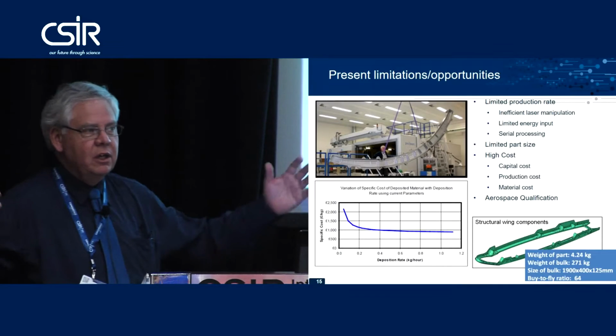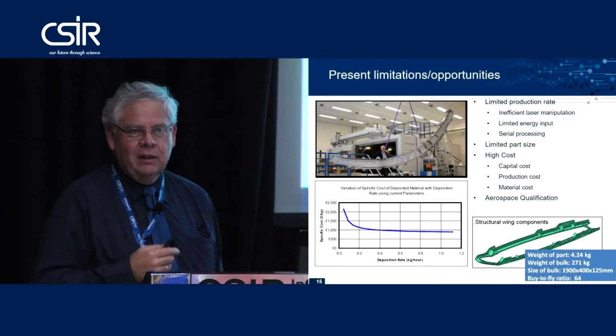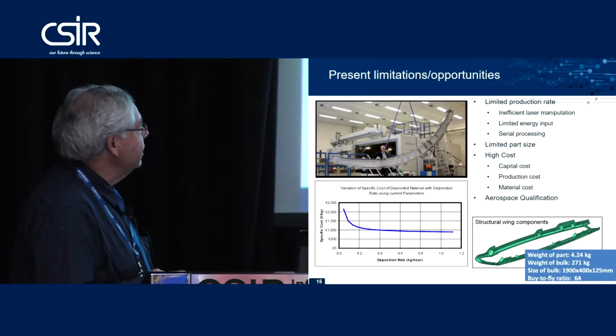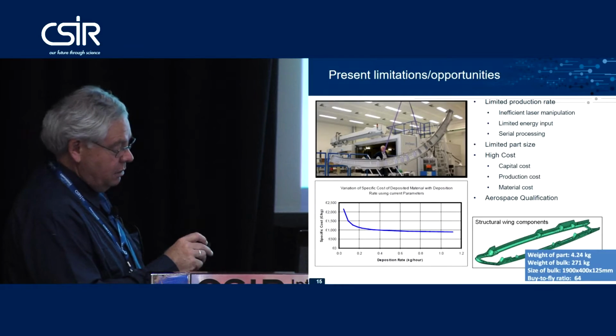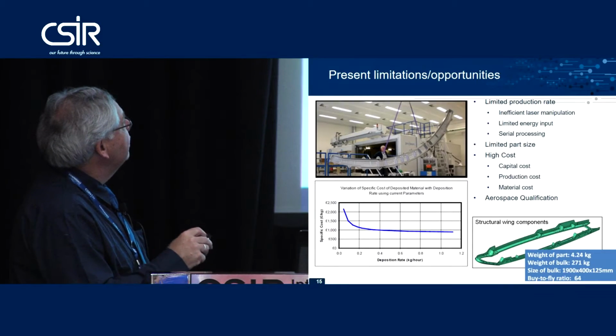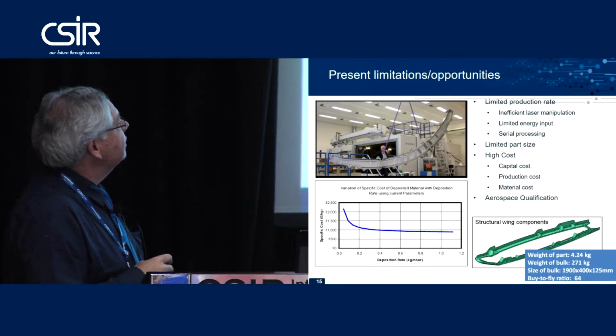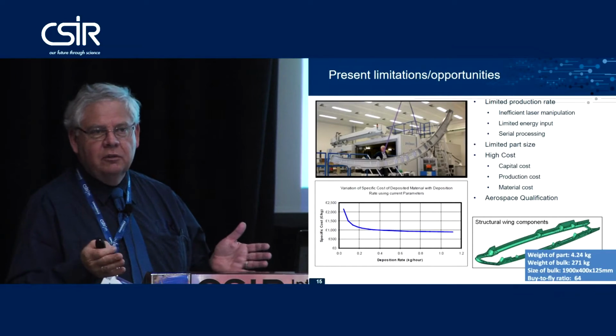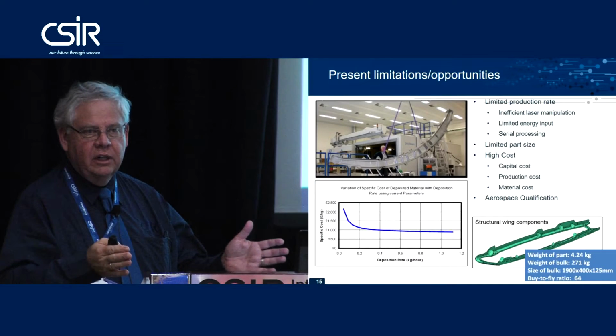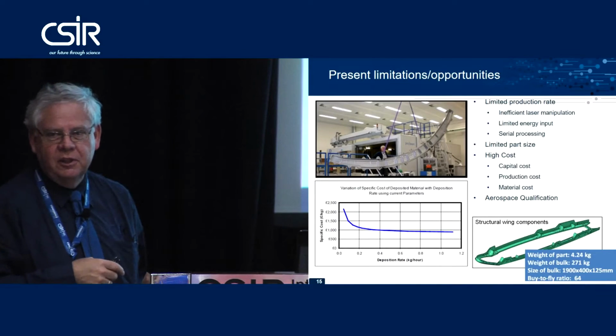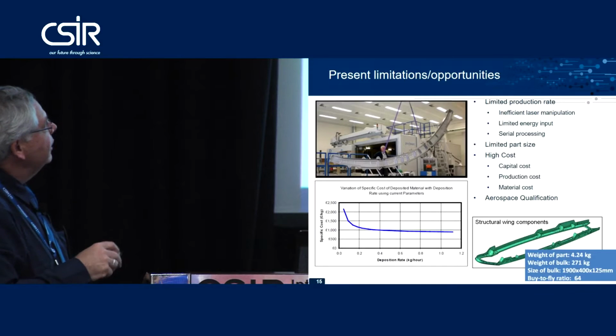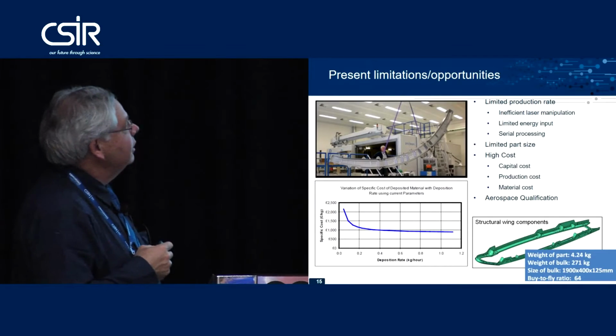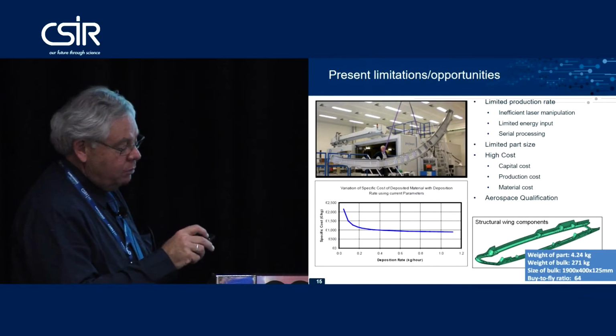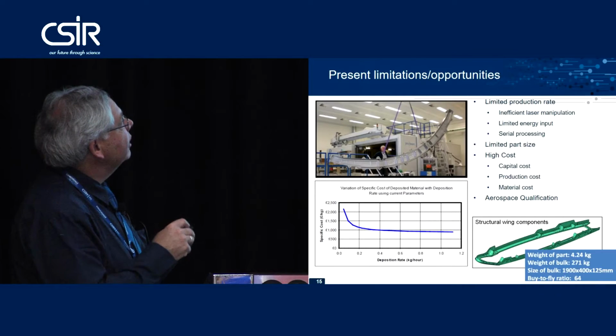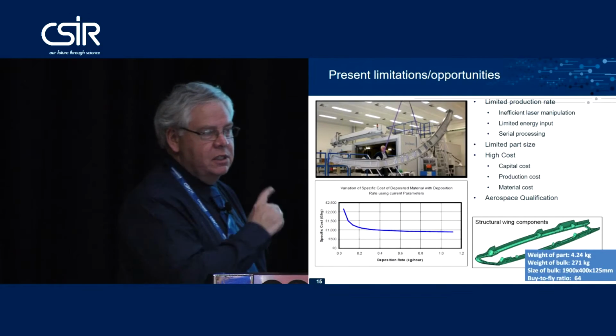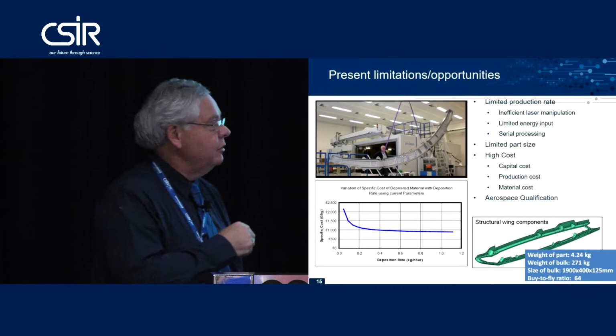So if you start thinking about very large aerospace components, you cannot really do this with additive manufacturing as yet. Just to give you an example, this is a part which I think is from Boeing in titanium, which is machined from billet. Currently, commercial systems in additive manufacturing do 300 or 350 by 350 by 350 millimeters. So a component like this is not possible. Now you can just imagine what big block of material you would have required to actually machine that component out. And this is typically a very good candidate for additive manufacturing.